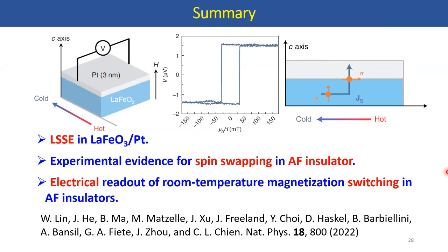My second question is, can we also explain this in light of thermal spin drag? For example, as we know, in some cases when we try to create an intense thermal gradient, there is also an out-of-plane gradient. So due to the out-of-plane gradient, maybe we are injecting out-of-plane spins and they are dragged sideways due to the in-plane thermal gradient. Is it possible or not? Yeah, I can assure that in our lanthanum ferrite platelet, even in the presence of the out-of-plane temperature gradient, during the in-plane temperature gradient, the contribution to the thermal voltage from the out-of-plane temperature gradient is negligible.